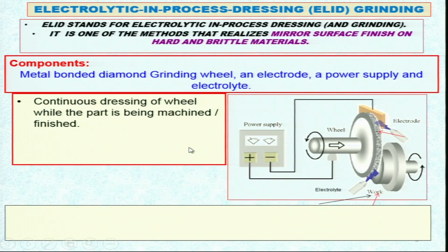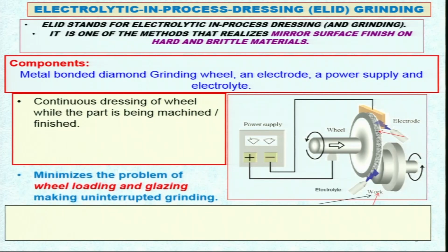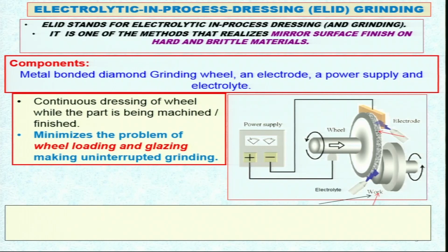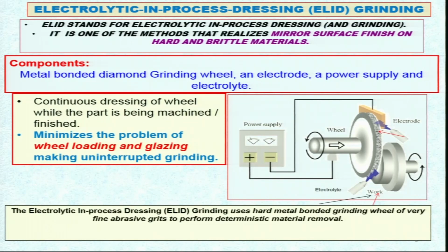Continuous dressing of wheel while the part is being machined and finished. This is an important feature of this process, that you are continuously dressing the grinding wheel when finishing is taking place, so that you need not stop the process and do the dressing of the grinding wheel. It minimizes the problem of wheel loading and glazing, because you are continuously dressing it during the process itself and making uninterrupted grinding. This is the unique feature of this process, because in general grinding you stop the grinding process, then you do the dressing of the grinding wheel, then you restart it. Here it is not required during the process itself. You can dress the grinding wheel and you can continue the grinding process.